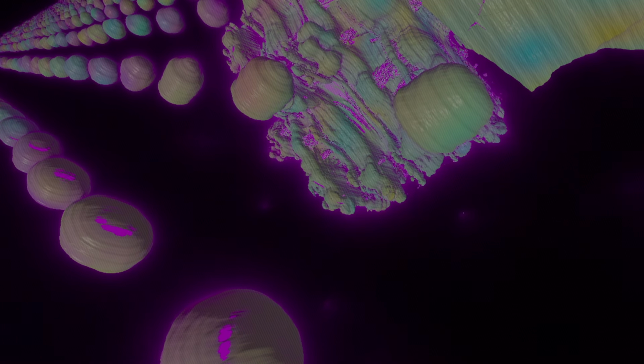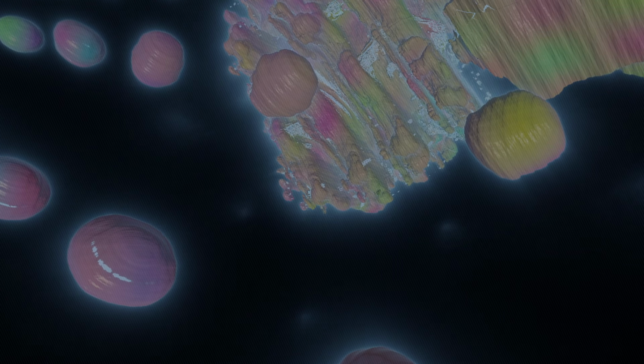And within these phonon collisions, there's this really crucial distinction between normal N processes and umklapp U processes. This seems critical for thermal resistance. It absolutely is. It's a subtle but profound difference. In normal processes, the total crystal momentum of the interacting phonons is conserved. Think of it like k1 plus k2 equals k3. All the wave vectors stay within that first Brillouin zone. N processes redistribute energy among the phonon modes, but they don't actually degrade the total momentum flux carrying the heat. So by themselves, they don't cause thermal resistance.